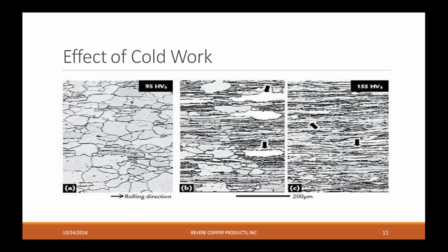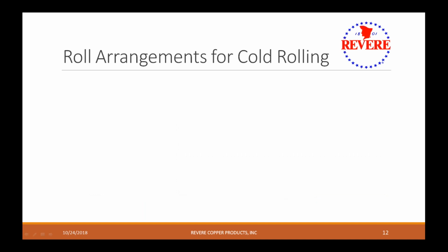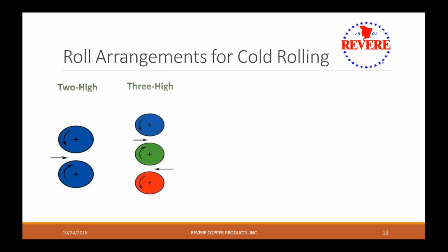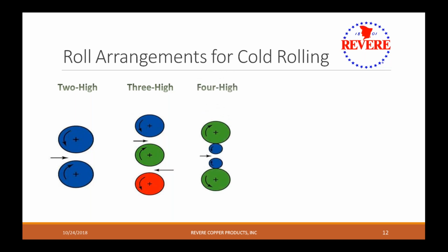So little slide on what cold rolling is. So we have many configurations for rolling mills. This would be a 2-high configuration. So in this case, you've got 2 big rolls that are putting pressure on the metal, which runs through the middle and does a gauge reduction. There's 3-high rolling. In that case, the metal is going in 2 directions. So it goes and it turns around a point and comes back, and you're rolling it 2 directions at the same time. A 4-high mill.